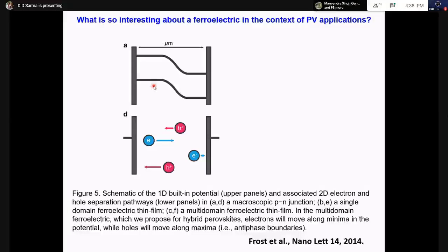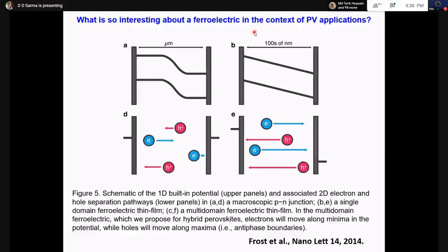But imagine if your material was actually a photovoltaic material, a ferroelectric material. A ferroelectric material has an internal polarization, which means the conduction band and the valence band across the domain run like this, such that it doesn't matter where you create the electron and hole. If you create the electron and hole here, the electron goes there and boom, it goes down there. The hole goes up. You do it here, the hole goes up, the electron drops down there. So there's an internal potential everywhere in the material that separates the electron and hole.